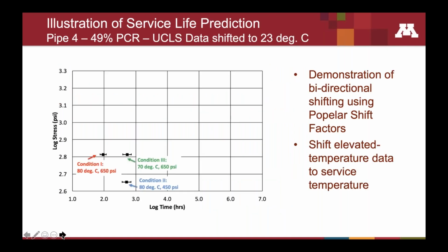So basically we would take testing at 3 different conditions, conditions 1, 2, and 3. Condition 1 was conducted at 80 degrees C, 650 psi stress in elevated water. The 80 degrees C is an elevated temperature water bath. Condition 2 is conducted at that same temperature, 80 degrees C, but at a lower stress of 450 psi. And condition 3 was conducted at 70 degrees C, a lower temperature, and at that same 650 psi stress as condition 1.